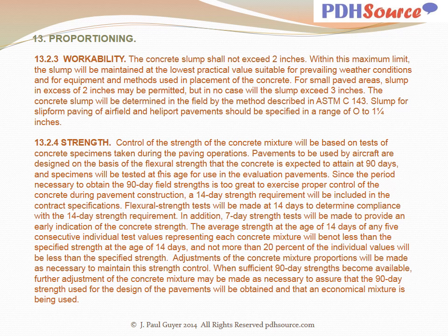Flexural strength tests will be made at 14 days to determine compliance with the 14-day strength requirement. In addition, 7-day strength tests will be made to provide an early indication of the concrete strength. The average strength at the age of 14 days of any 5 consecutive individual test values representing each concrete mixture will be not less than the specified strength at the age of 14 days, and not more than 20% of the individual values will be less than the specified strength.